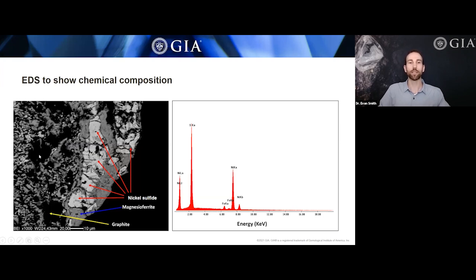And we can see, just based on the difference in backscattered electrons, different shades of gray. So this black here is due to the diamond itself. There's also black here that's just the carbon present in graphite. There's a medium gray phase here that corresponds to magnesioferrite, but it's this brighter gray phase that we're interested in. So this is what we were seeing in the X-ray diffraction data. And here, using EDS, we can produce this spectrum that shows the characteristic X-rays emitted by different elements, different atoms that are present in this material. And we can see that it's made up of nickel and sulfur, plus a little bit of iron too. So this allows us to identify what it's made of.